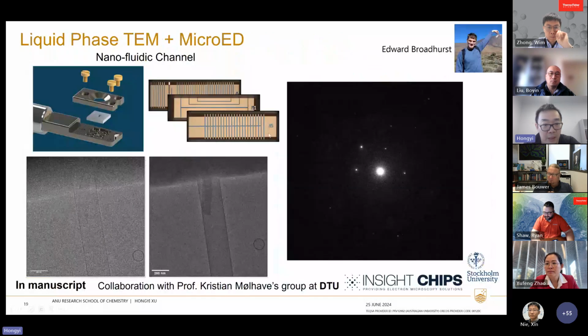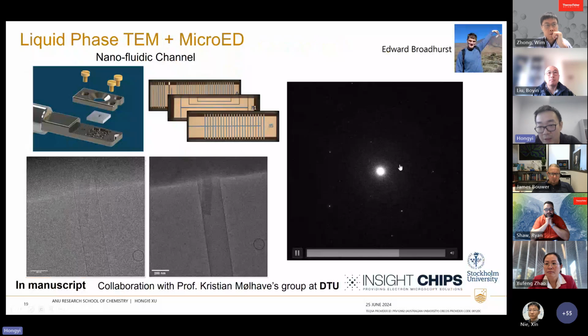And we can also now work with samples in liquid. So this is a collaboration with a group at DTU, Kristian's group at DTU, and also they commercialize the chips nowadays. So these are nanofluidic channels. What you're looking at here is these are the silicon nitride film glued together. And then in this channel, there's about 200 nanometer depth, and the liquid can run through this liquid channel. So this crystal you're seeing here is actually submerged in liquid. And in this case, the crystal is in air, so there's no liquid in the channel. But in this case, the channel is filled with liquid. So with this, we can study crystals in different chemical environment. And because of diffraction, different to imaging, right?